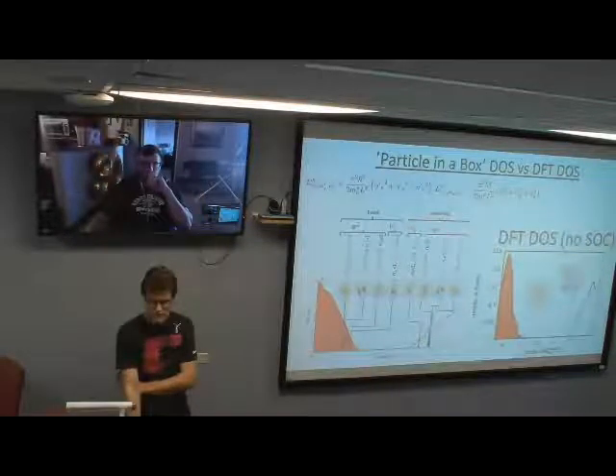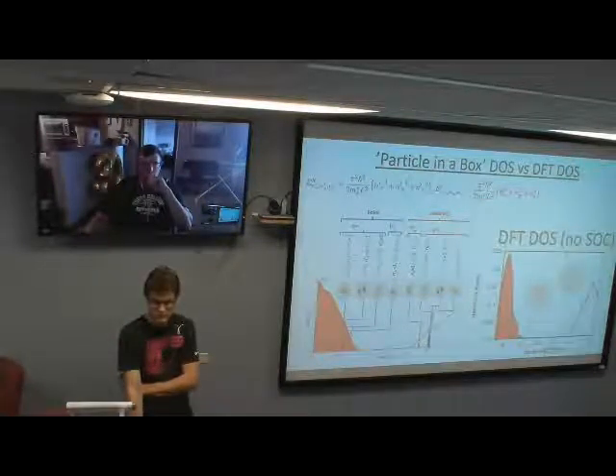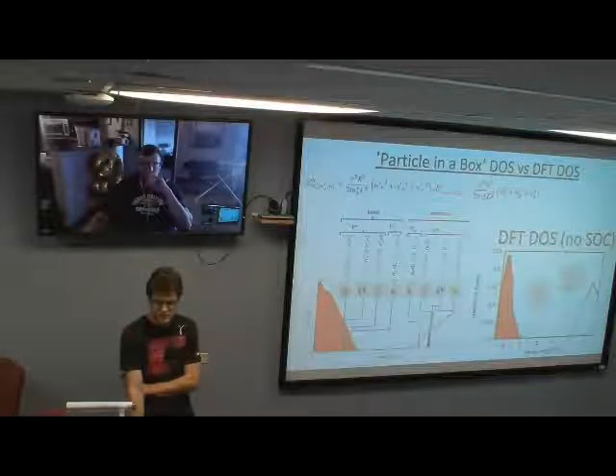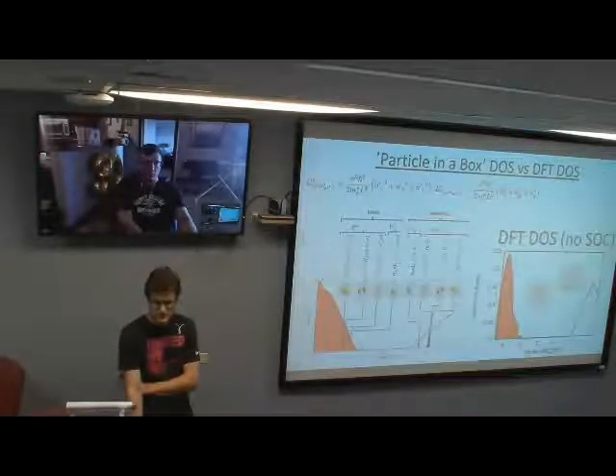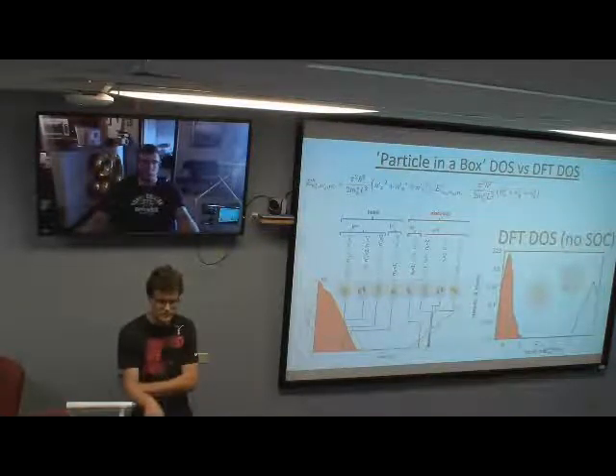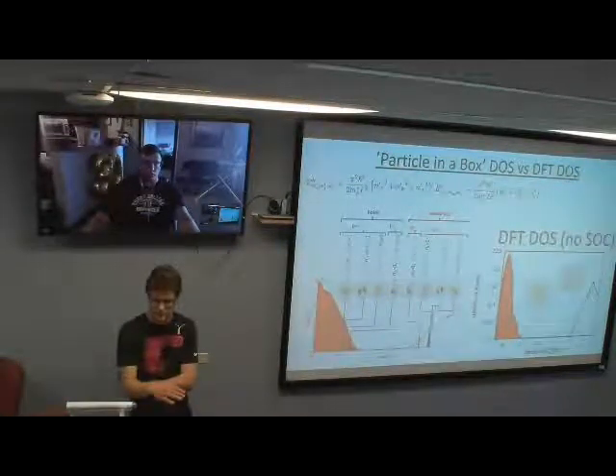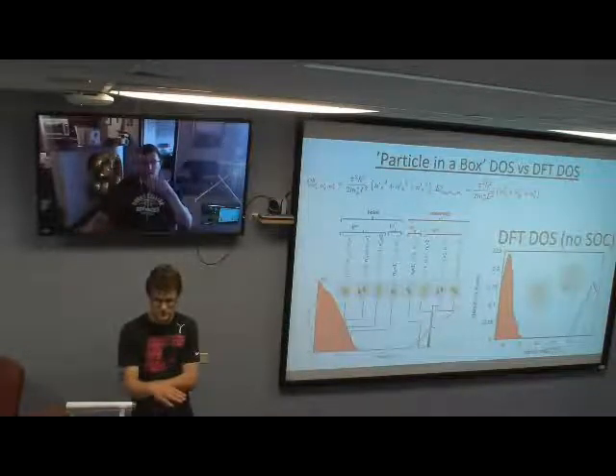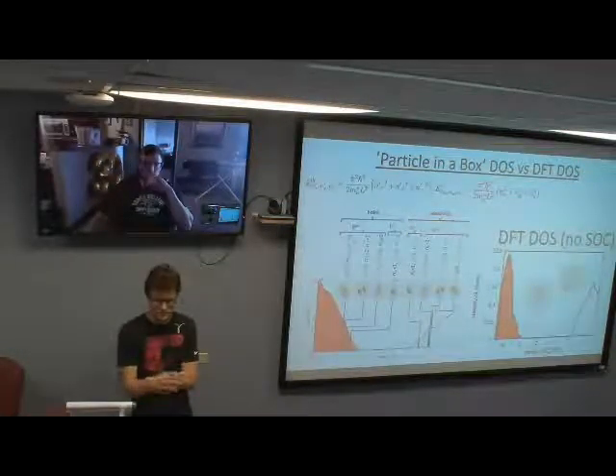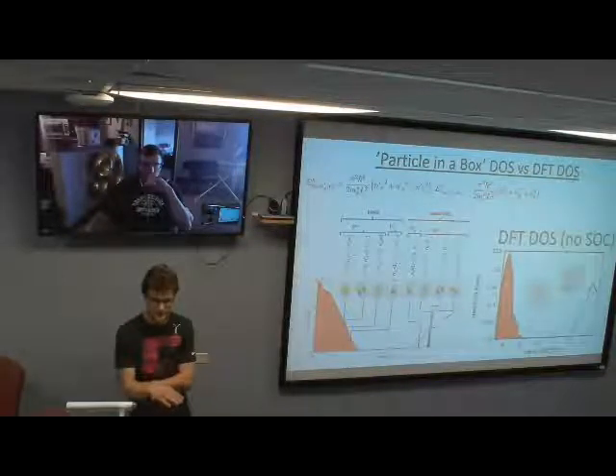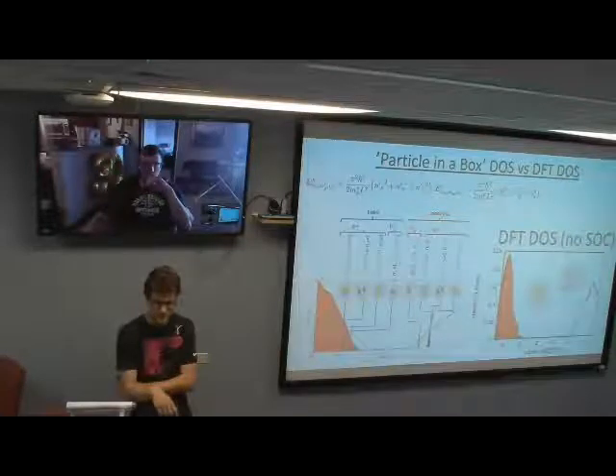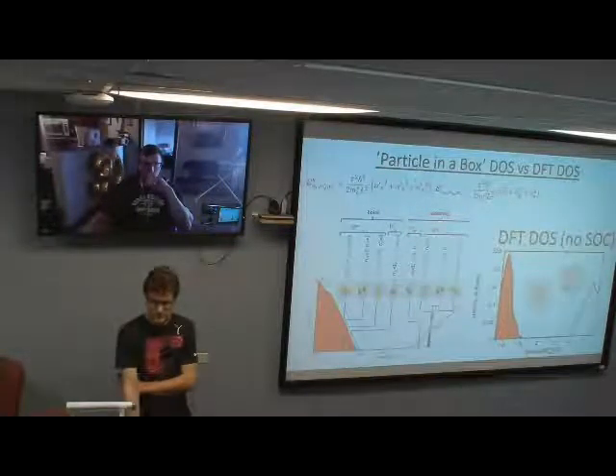Because if it's higher, then we actually have a classical case. If it's low, then we have this tunneling, and your wave function will have an exponential kind of shape, right? Mm-hmm. And inside it will be a perturbed solution of the infinite box solution. I don't remember, I think it decays. It decays exponentially. Oh, yeah, it decays, right? Like 5 angstroms, I think it's mostly, at least for the calculations I remember. Anyway, it was like 5 angstroms. That's where most of the density is, and it's very low outside the box. But it probably should decay much slower.